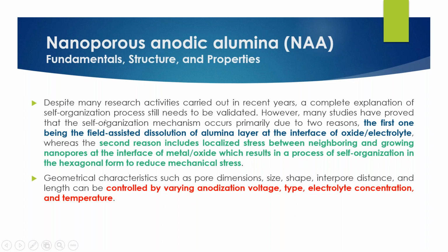However, many studies have proved that the self-organization mechanism occurs primarily due to two reasons. The first one being the field-assisted dissolution of alumina layer at the interface of oxide electrolyte. Second reason includes localized stress between neighboring and growing nanopores at the interface of metal oxide, which results in a process of self-organization in the hexagonal form to reduce mechanical stress.